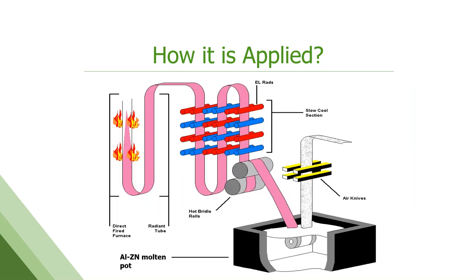This is sort of a blown up diagram of the furnace and pot section. This is really where all the action happens on these production lines. This happens to be a diagram of the Steelscape metallic coating lines, which are direct fired furnace. Not all lines are direct fired furnace, but this one is. We're actually impinging flame onto the strip. Helps anneal the steel, clean the steel, get it to its right properties. Goes through a set of radiant tubes and electrical tubes at different temperatures to finalize and set those mechanical properties in place. And then this strip comes down into the molten bath. The strip temperature is very, very critical, and the temperature in the pot is very critical to get this metallic coating to adhere. And then it goes up through the air knives to get its correct coating weight.